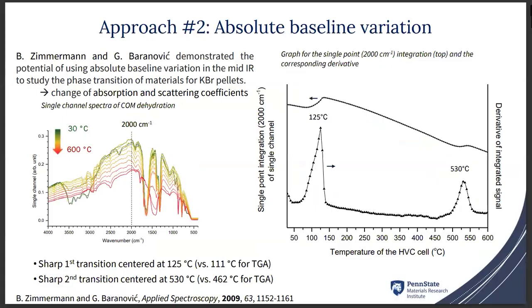That's why we decided to use a second approach, discussed by a group in 2009, where they demonstrate the potential of using the absolute baseline variation in the mid-IR to study phase transition of material for potassium bromide pellets. This has to do with the fact that at the transition temperature, we have a change of absorption and scattering coefficient, leading to a change of the baseline. So we can only look at the single channel in an area where there is no vibrational band, so 2000 reverse centimeter was used.